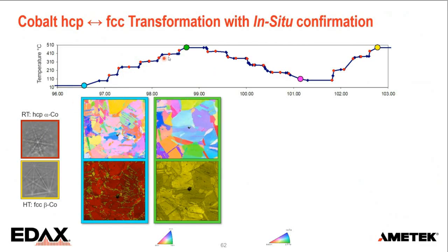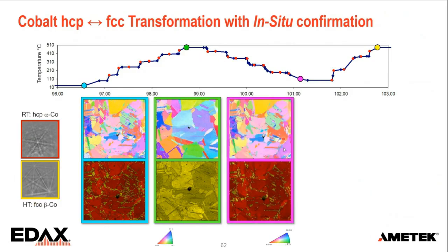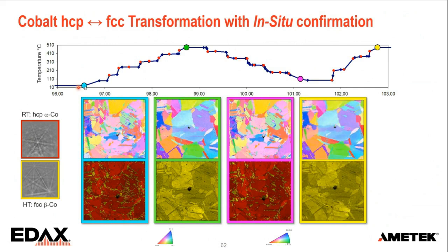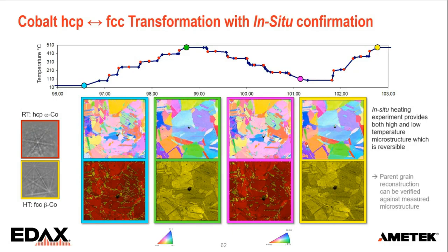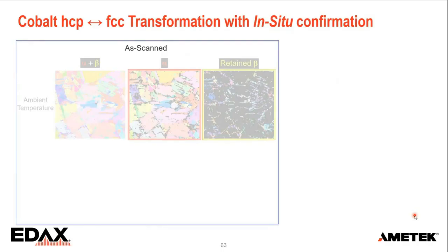At high temperature, we went through this phase transformation and you get the cubic structure. It's all yellow, indicated here by the yellow border around that pattern. Then we cool down, and it goes back to the low temperature hexagonal structure again, and so on. So we can just keep going up and down. The special thing about this data set is that this microstructure is reversible. So it doesn't recrystallize at these temperatures, and it just flips from hexagonal to cubic and back again. And that makes it an ideal test case to see how good the parent grain reconstruction is. So when we look at that, this is as scanned.